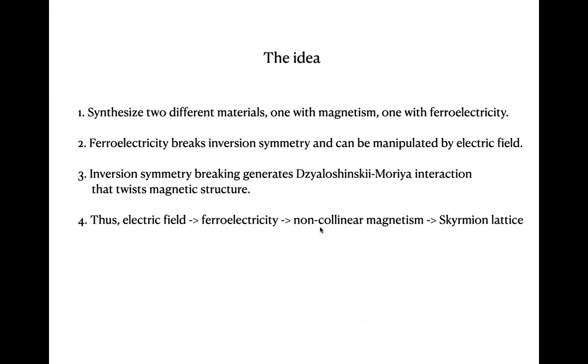So what is the idea? The idea is to synthesize two different materials, one with magnetism, the other with ferroelectricity. The presence of ferroelectric order automatically breaks the inversion symmetry and can be manipulated by electric fields. The inversion symmetry breaking will generate the so-called Dzyaloshinskii-Moriya interaction between the local moments.